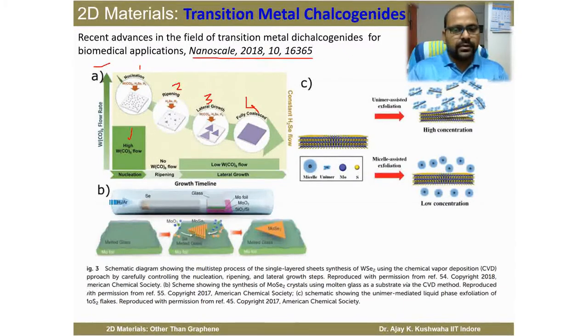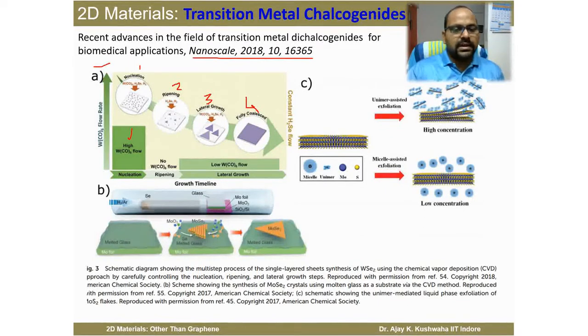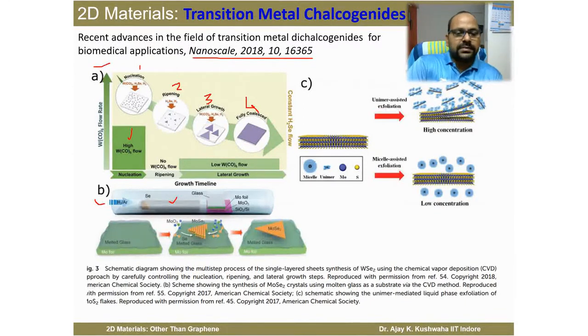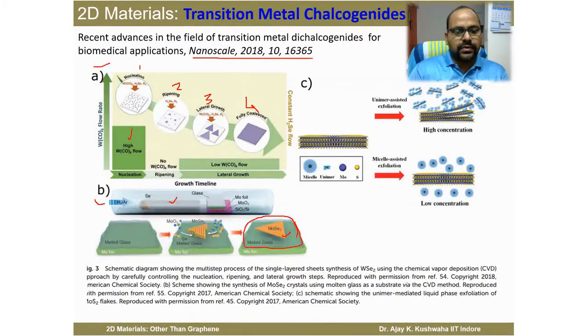A very small amount of W(CO)₆ is then supplied to initiate lateral growth. Supplying the precursor for a longer time causes it to cover the entire surface. In another approach, growth of MoSe₂ was reported where selenium was placed in a boat and a molybdenum foil was placed on top of a glass substrate. The molybdenum and selenium react and deposit over the melted glass, with Mo at the bottom, then the melted glass, then MoSe₂ on top.